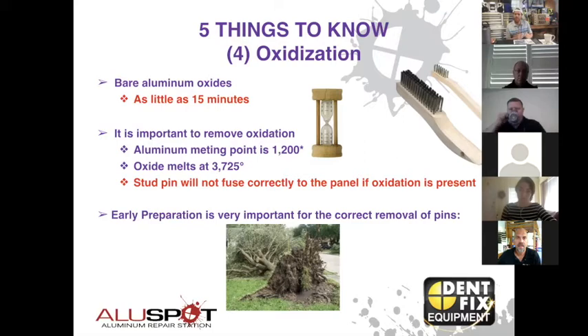I use this tree as an example. If you have an aluminum pin that you stuck into your aluminum panel and it got roots, I mean, it really dug down into that aluminum, either because the power setting was too high or because you didn't get a clean weld because the aluminum corroded or it had too much oxidation, and you go to remove that pin, guess what's going to come with it? All the roots. You're going to pop a hole in that aluminum panel and create damage that's going to be seen later down the line.